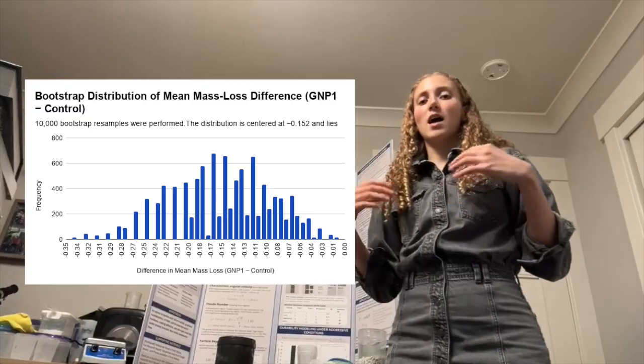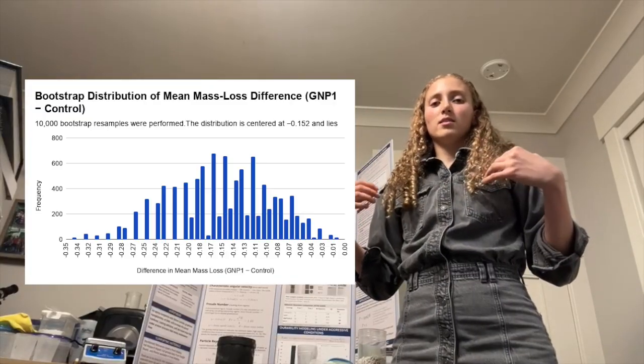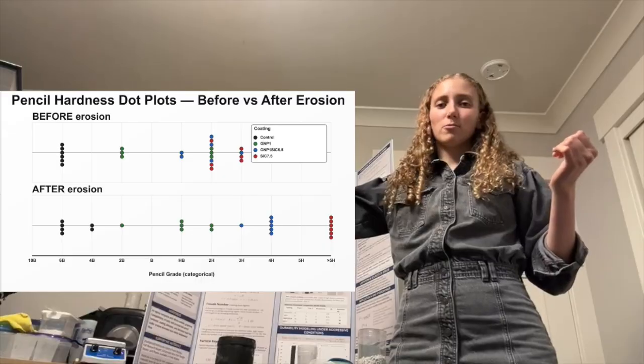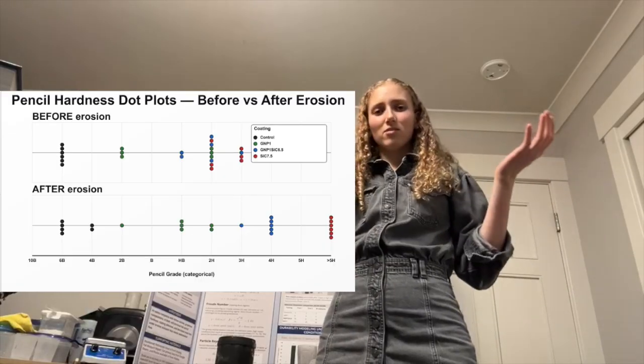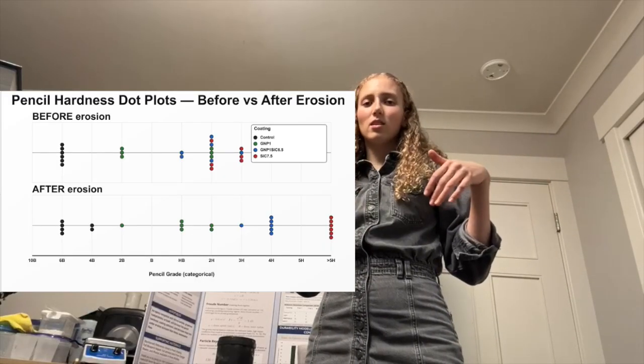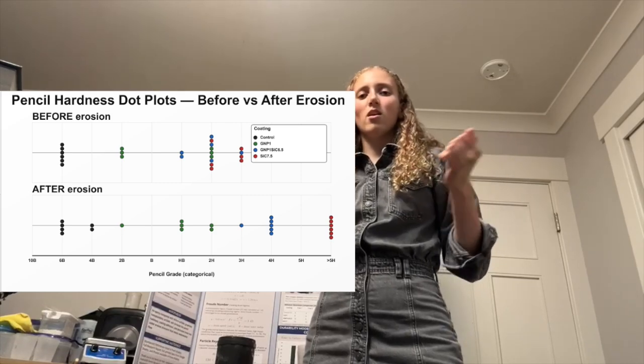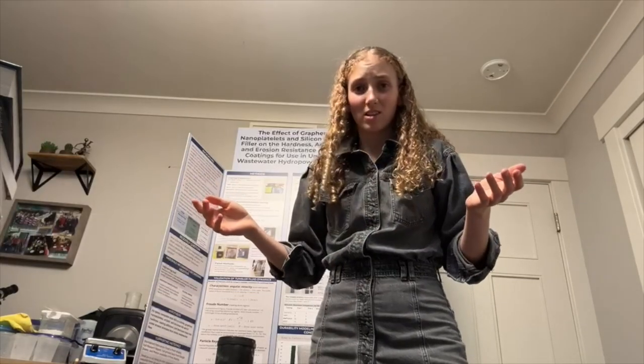significance for 10,000 resamples. Silicon carbide had the highest hardness before and after erosion, but didn't have the lowest mass loss, illustrating that high hardness particles don't always perform the best in erosive conditions.